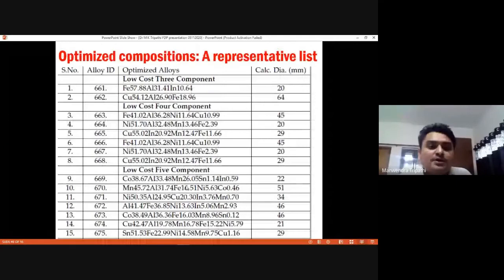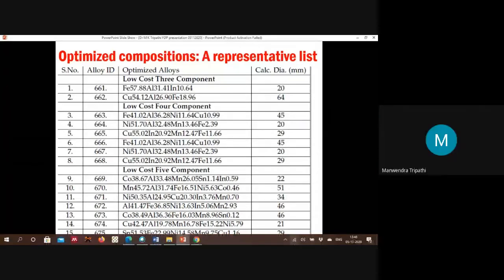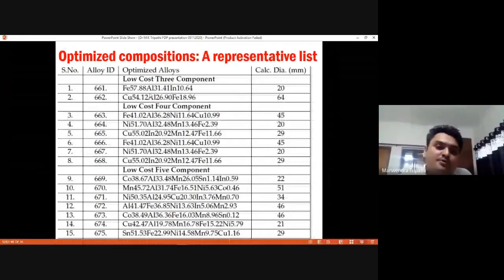And these are the typical results we are getting. For example, this is a 3 component system, 4 component, and 5 component systems. These are the predicted compositions, and this is the calculated diameter. Calculated, I mean this is the expected diameter of the metallic glasses, right? But we do not rely on that. Okay, our code has given this composition, so let us experimentally validate it.